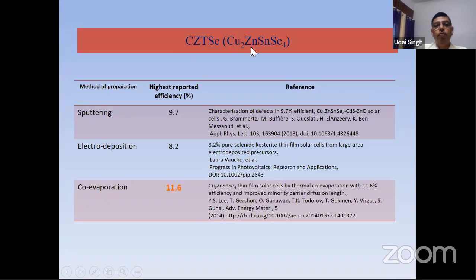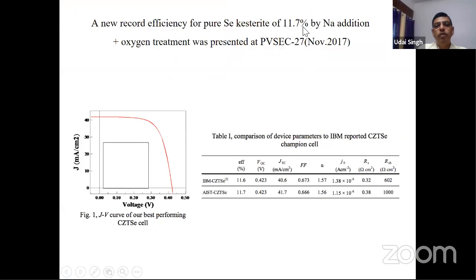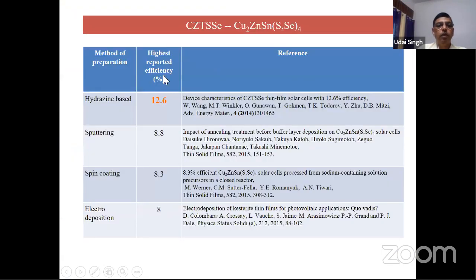If you have this variant, copper zinc tin selenide, with the different methods we use, the highest efficiency achieved is only 11.6%. This 11.6 has been improved to 11.7, not much. And now for copper zinc tin sulfur selenide, the highest efficiency is 12.6%. This is the highest, achieved in 2014 only on a small area, and in the last 6 years this has not been improved. People are struggling. They're trying to get around 9 to 10% only on the small area. So there is no possibility of any module manufacturing either.